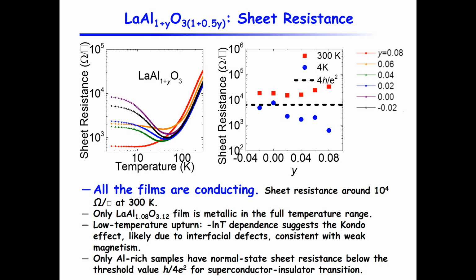The fact that we grow these at 37 millitorr oxygen pressure and still get them conducting has not been demonstrated before. I think that's because our technique allows us to grow layer by layer at this pressure. And this is the quantum critical resistance for superconductivity. I think it's in general consistent with what people have seen, for example Darrell Schlom's group, that you need aluminum-rich compositions to get superconductivity. We get them all conducting, but you do get lower resistance, at room temperature and at low temperature too, when you go to aluminum-rich.